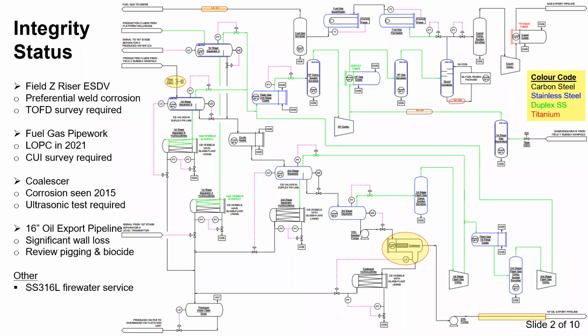Thanks, Ross. So just to provide a brief overview of the integrity history that we have received and a few key focus points that we picked out from that data. First of all, starting with the riser ESDV on field Z, on the far right-hand side of the slide. It's been previously identified there's preferential weld corrosion there. So we'd recommend doing a TOFD survey to identify how developed that corrosion is, and then we can assess the risk specifically for that. Another point is the fuel gas pipework, at the top of the diagram. There was a loss of primary containment in 2021 due to external corrosion. So we recommend that we do a survey of corrosion under insulation to ensure that we don't see that mechanism again and have another loss of containment.